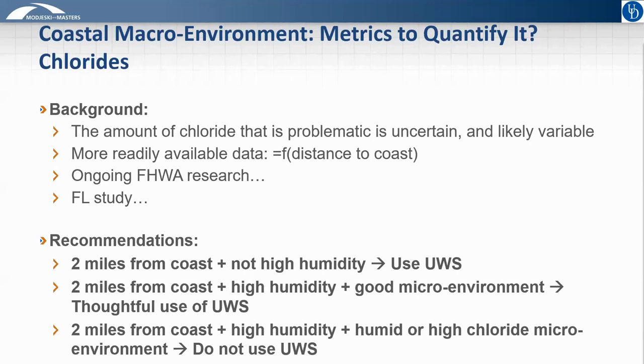So this information, combined with the relative humidity data and considering microenvironments, leads to alternative recommendations depending upon whether just one of these parameters is severe. If just distance to the coast is low, but there's not high humidity, the use of uncoated weathering steel is recommended. Or conversely, if we have high humidity but we're more than 2 miles from the coast, that also indicates acceptable performance of uncoated weathering steel. But as 2 or 3 of those parameters of coast, high humidity, and the microenvironment start to interact, we become more restrictive on the recommendations on the use of weathering steel. So if only 2 of those parameters are maximized, we recommend thoughtful use of uncoated weathering steel. And if all 3 of those parameters are severe, the recommendation is to not use uncoated weathering steel.